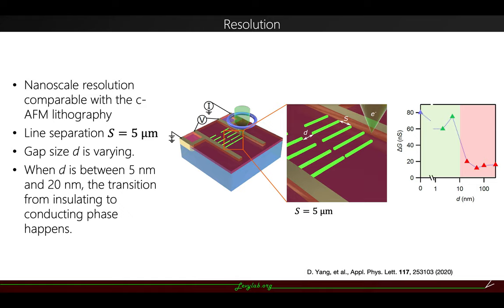So it's natural to ask the question, what's the resolution of this writing process? To do that, I designed this structure which contains a series of nanowires. The nanowires are separated by 5 micrometers apart to suppress the cross-talking between each other. There's a gap in the middle of the nanowire. And here,